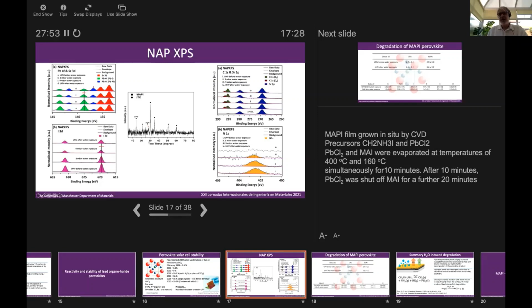The nitrogen 1s is the most spectacular change. So this is the nitrogen 1s for our pristine sample. We see a fairly strong peak. As we expose to 3 millibars, there's not much of a change, but at 6 millibar, this peak starts to decline rapidly. And when we pump away the water, it takes maybe 3 or 4 hours for the chamber to return to ultra high vacuum, so there's still a little bit of water vapor in that cell. So this will have been exposed to water vapor for quite some time. We see this has completely disappeared. Now 9 millibar was chosen because this corresponds to approximately 30% relative humidity at 25 degrees centigrade.